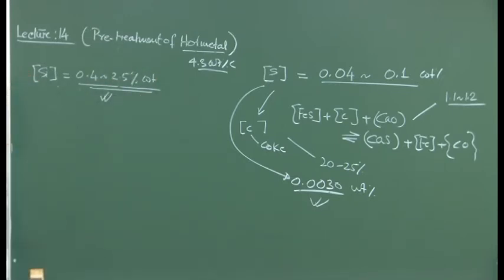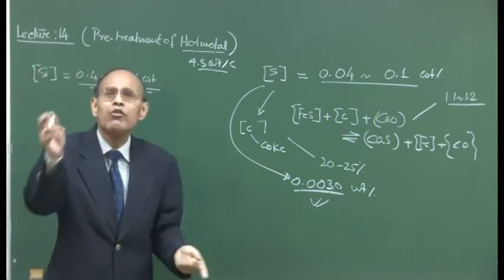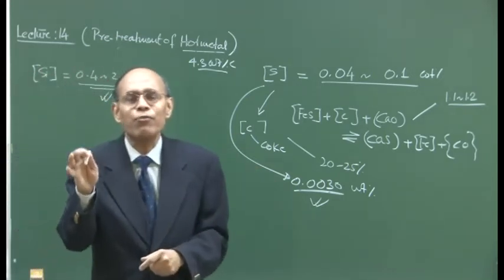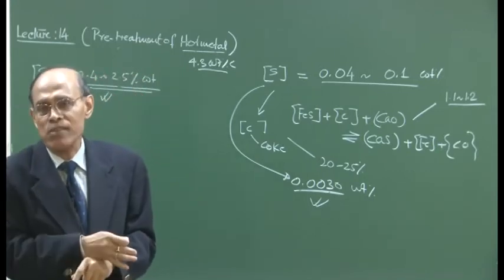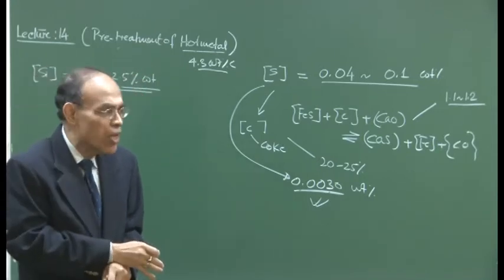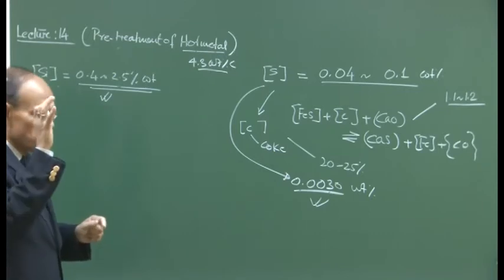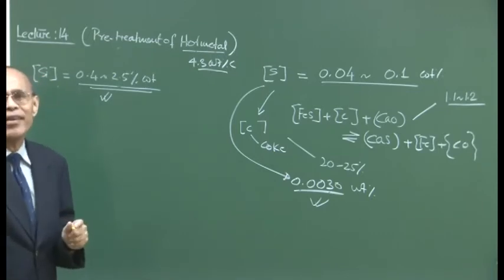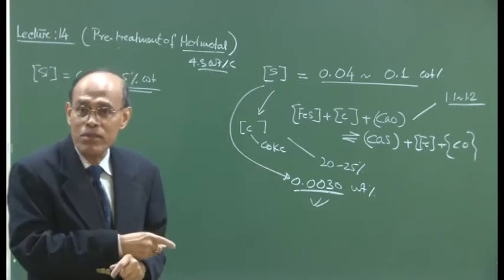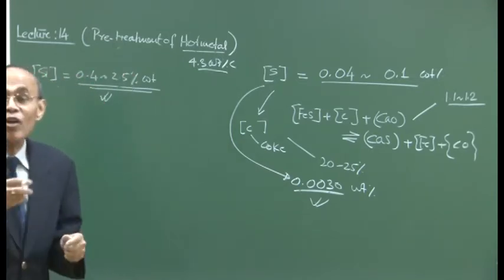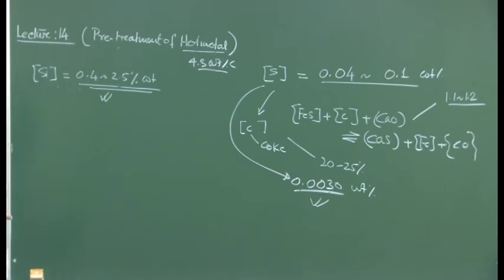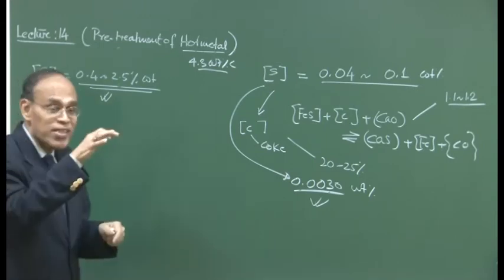In some plants, not only silicon is removed, not only sulfur is removed, but also phosphorus is removed. We will see that for steel making, removal of phosphorus is not an important issue at all. All the conditions necessary for phosphorus elimination are satisfied in steel making. While in blast furnace, we cannot even eliminate 1 ppm of phosphorus, because phosphorus elimination requires an oxidizing environment and high basicity, and blast furnace has reducing environment.